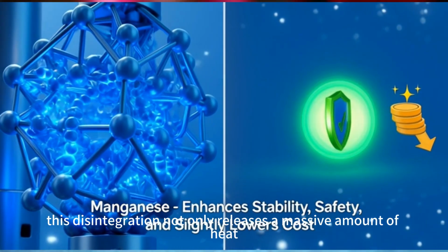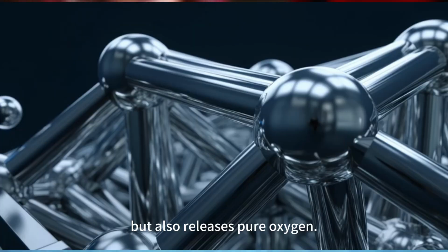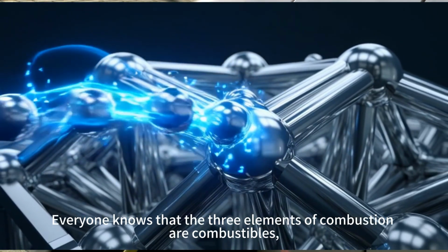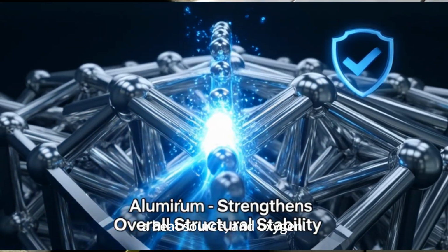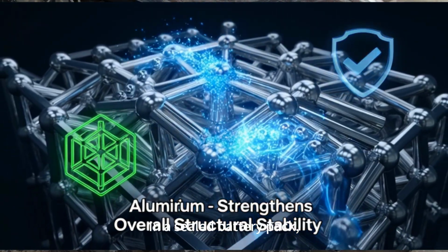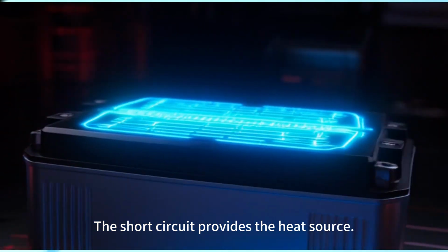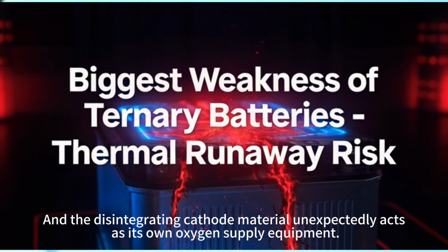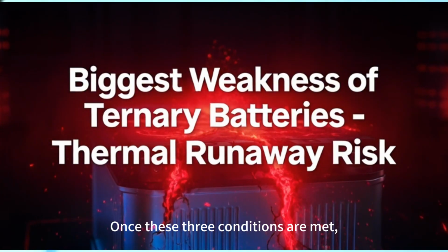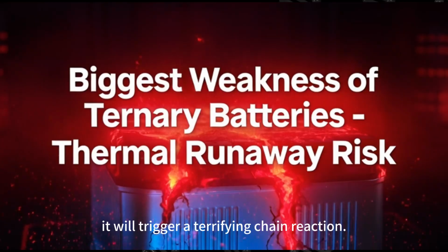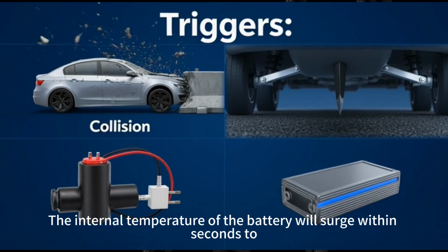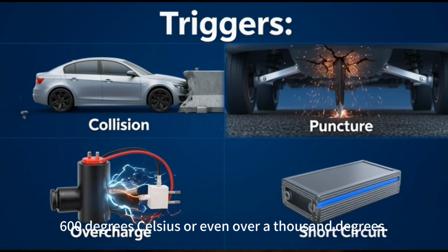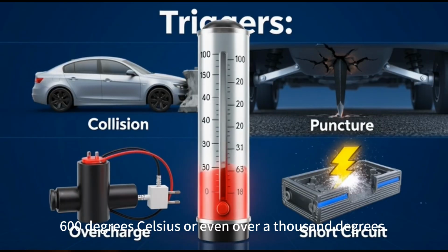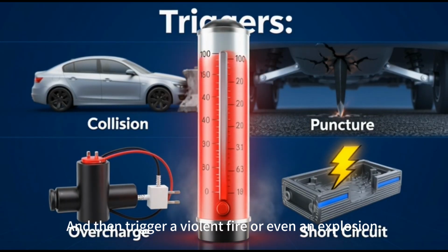What's even more terrifying is that this disintegration not only releases a massive amount of heat, but also releases pure oxygen. Everyone knows that the three elements of combustion are combustibles, a heat source, and oxygen. In a sealed battery pack, the high-temperature liquid electrolyte is an excellent combustible. The short circuit provides the heat source, and the disintegrating cathode material unexpectedly acts as its own oxygen supply equipment. Once these three conditions are met, it will trigger a terrifying chain reaction. The internal temperature of the battery will surge within seconds to 600 degrees Celsius or even over 1,000 degrees, and then trigger a violent fire or even an explosion.